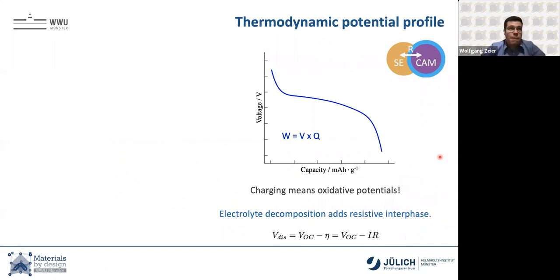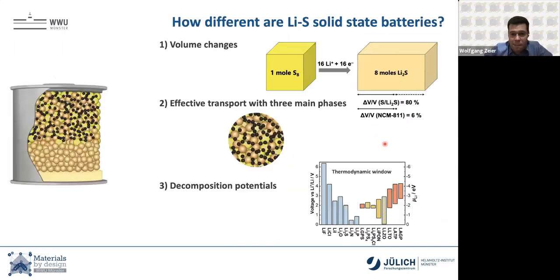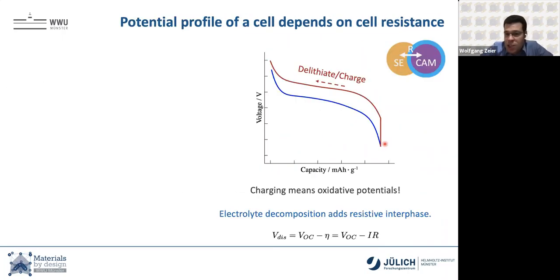Why is this a problem? Well, decomposition. This is a schematic charge-discharge curve, voltage versus the capacity, the area underneath. So you would discharge a material, the area underneath is the energy that you get out. Now, in reality, you have a resistance between your electrodes. So when you charge your material, you get some sort of overpotential.